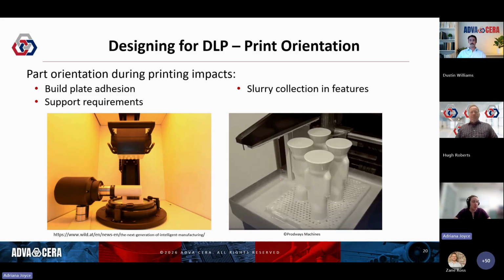On the Lithoz printer, the part is hanging upside down, and the vat has only enough slurry for a single layer, every layer. It's very efficient in terms of slurry use, and it actually allows the slurry to drain out of open features because they're hanging upside down. But it also means that we're fighting gravity with every layer because of the weight of the part. And any feature that closes up before the print is finished traps any remaining slurry inside it, facing the build plate. It also means that the face of the part that's attached to the build plate needs to be large and flat, or we have to add some supports to keep it attached to the build plate. Overhangs have to be able to support themselves against gravity, or we have to add supports to keep them from flapping around.